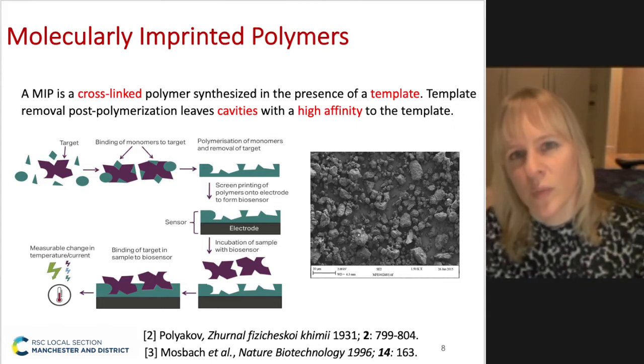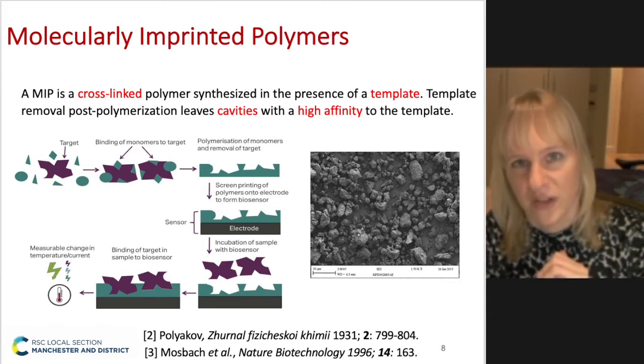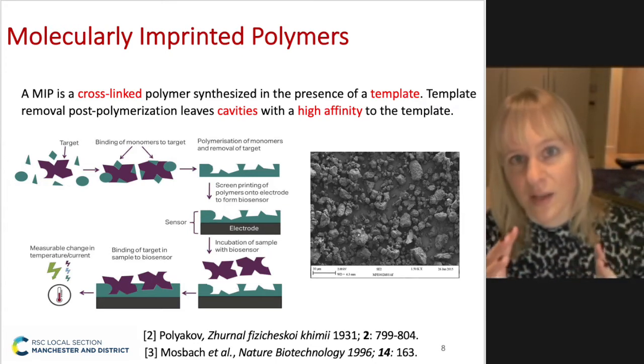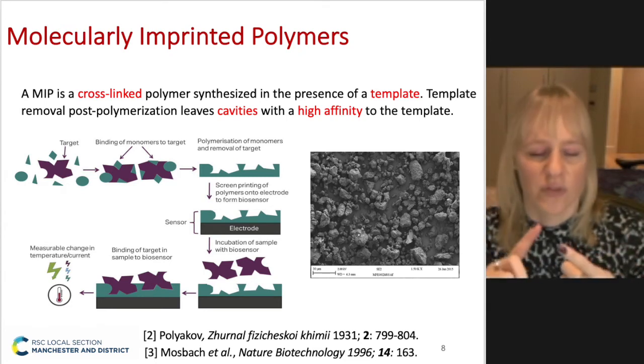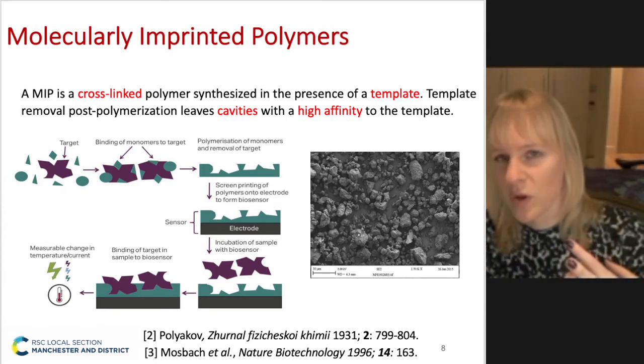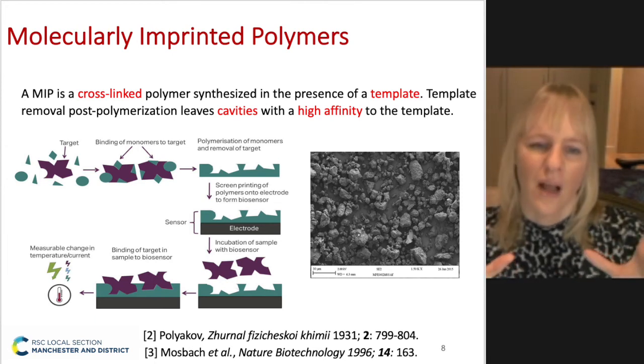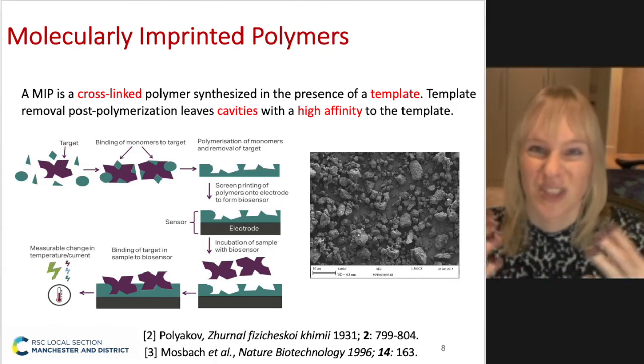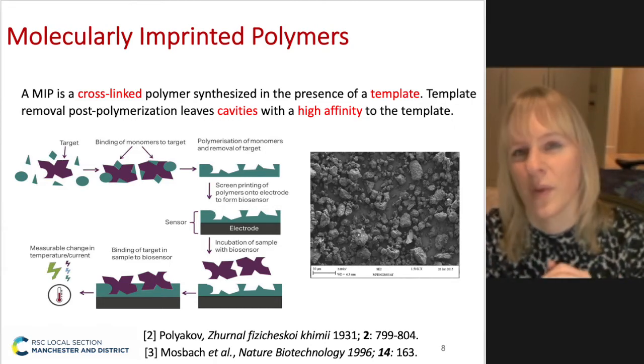After the polymerization is complete, we extract them from the matrix, leaving particular monomers that can selectively recognize the target afterwards. This is a combination of size, shape, and chemical functionalities. The 3D matrix — the polymer structure — is what gives these binding sites their rigidity and stability in order to remain intact.